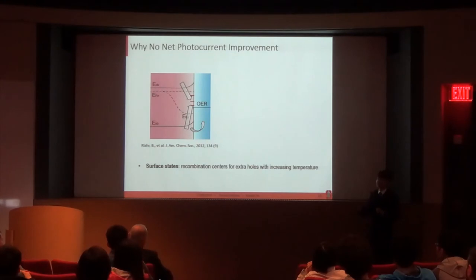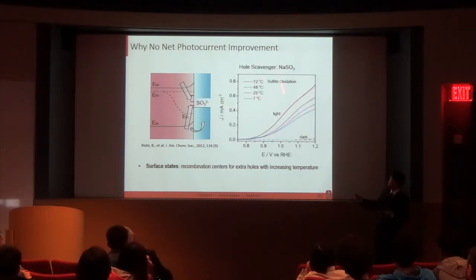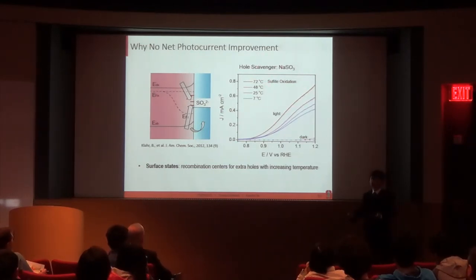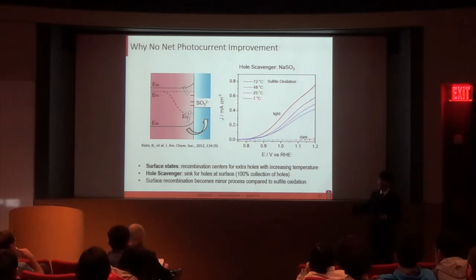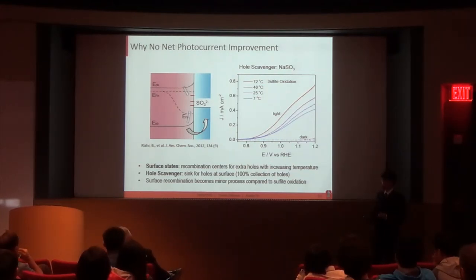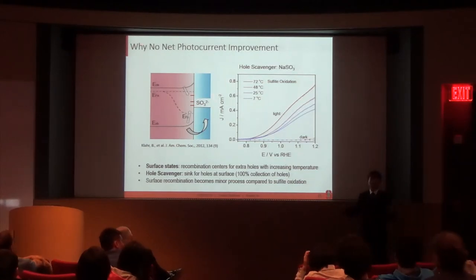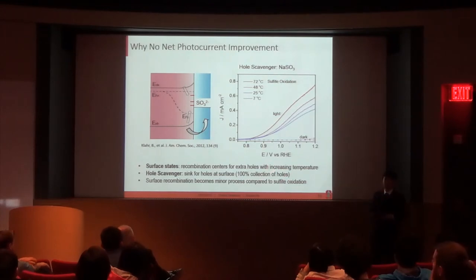To confirm this hypothesis, I added a hole scavenger, sodium sulfite. The sodium sulfite replaced the water oxidation reaction with the sulfite oxidation reaction, which is kinetically much faster. In fact, it serves as a sink for the holes that can reach this surface. Typically, it is assumed that the hole scavenger can give you 100% collection of holes, so that the surface recombination now becomes a much more minor process as compared to sulfite oxidation.